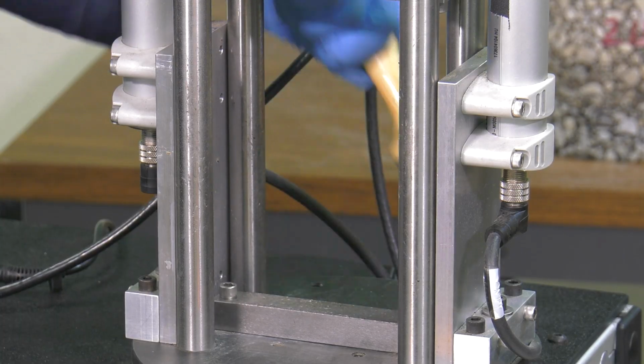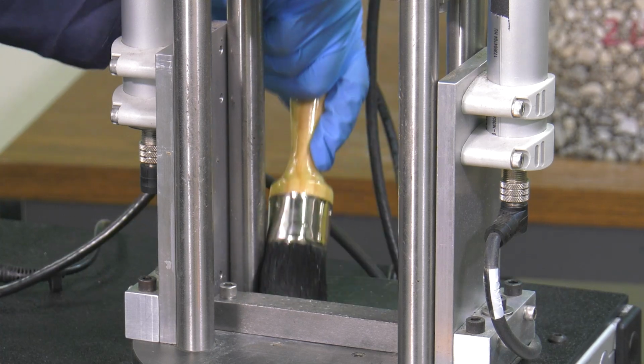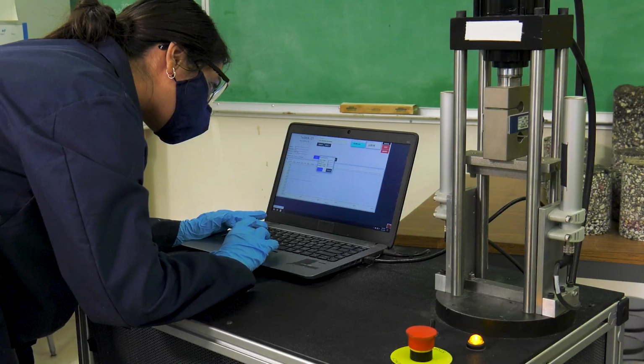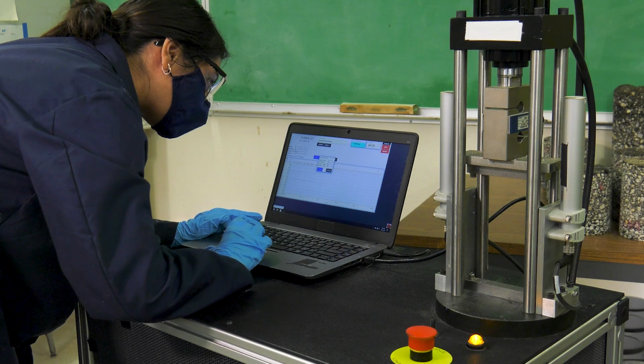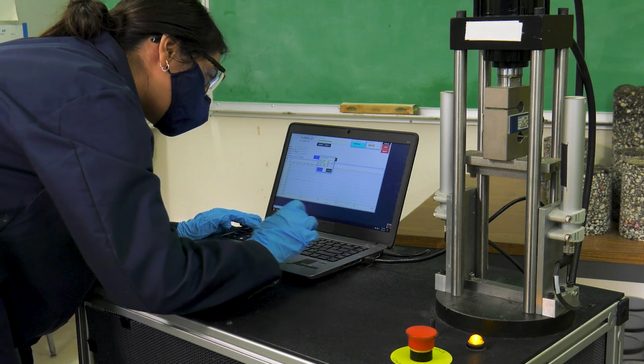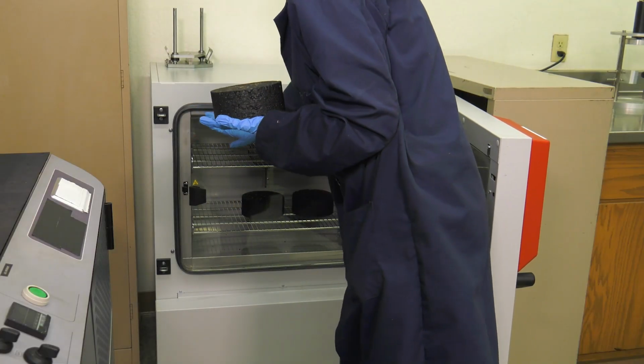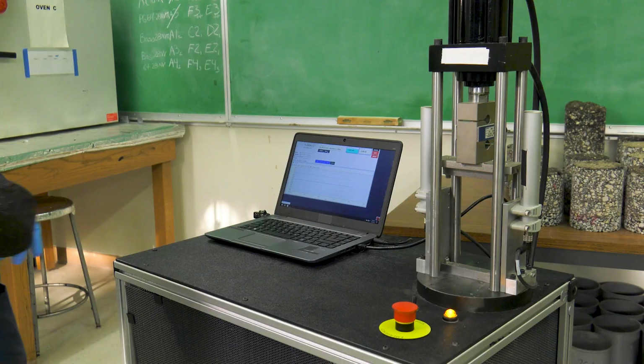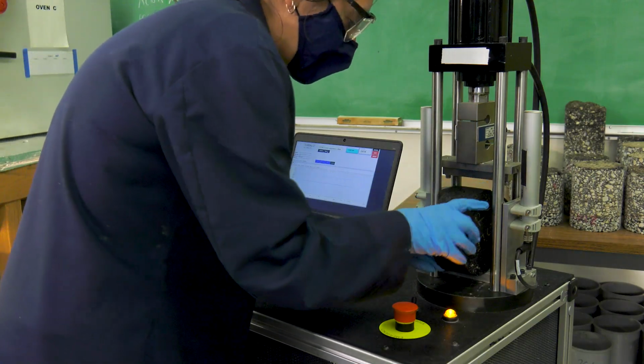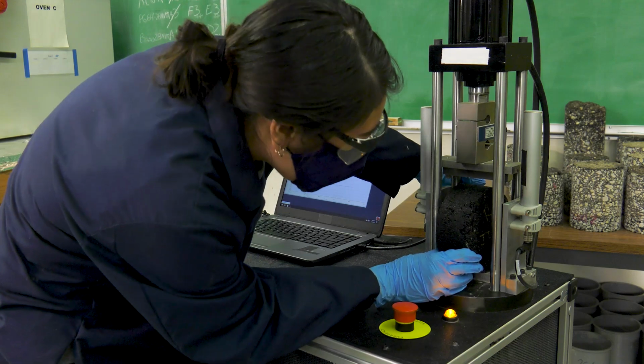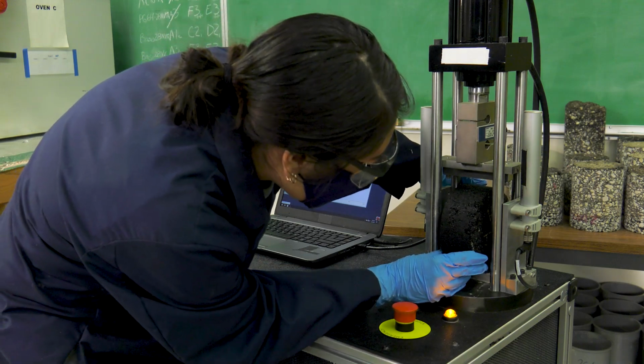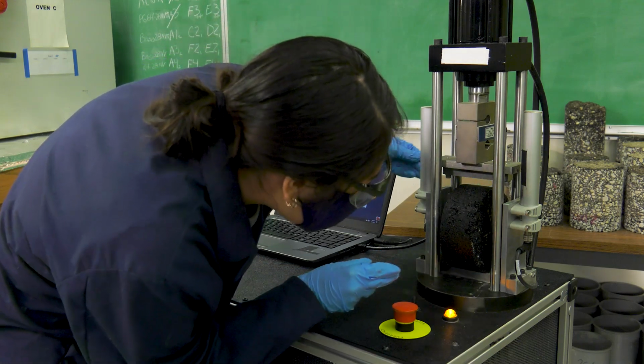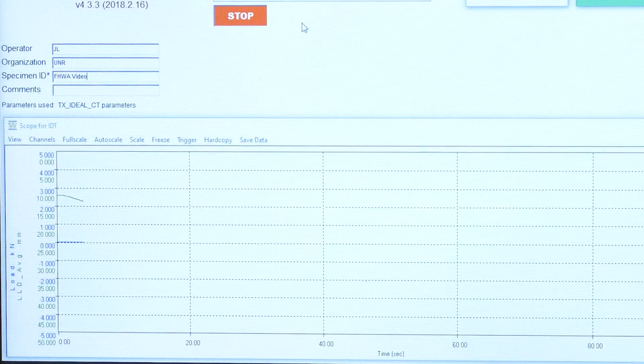Inspect the fixture to ensure all contact surfaces are clean and free of debris. Before starting the test, enter the specimen and test information in the control software. Remove the specimen from the environmental chamber and quickly mount the specimen in the fixture. Visually inspect the specimen to ensure it is centered and making uniform contact on the support strip. Begin the test.